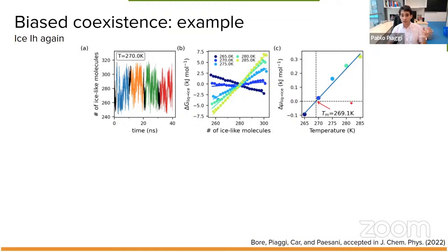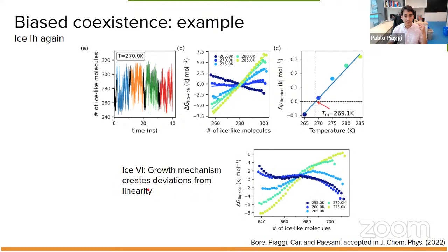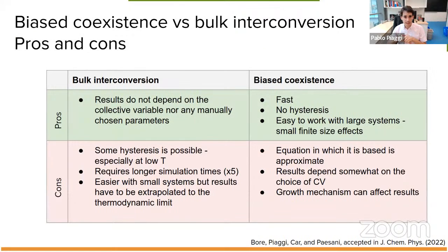So this looks very good, but of course there are more complicated cases, and I would like to highlight, for instance, one of the phases that we studied, that is ICE-6. In this case, one can see that the growth mechanism definitely interferes with the expected linearity of the free energy profile, but still by averaging over one layer, one should be able to remove this effect. Okay, so this is the biased coexistence technique.